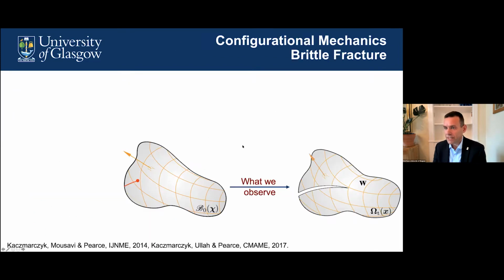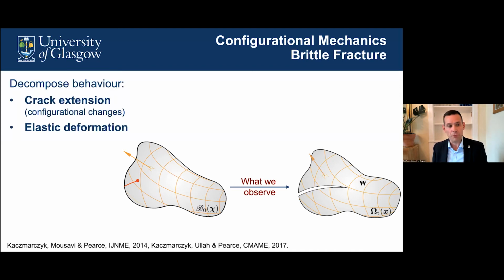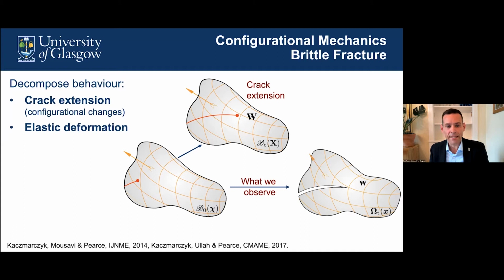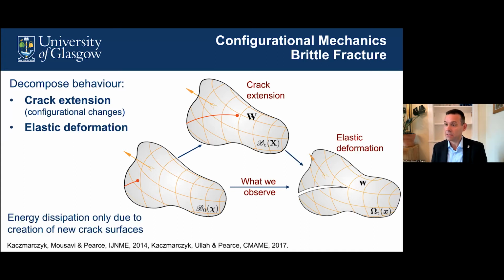Configurational mechanics in a nutshell: if we take a body subjected to load, what we observe is elastic deformation and crack propagation. What configurational mechanics allows us to do is to decompose the problem into a crack extension and the elastic deformation. We decompose the problem into these two cases, whereby all the energy dissipation is only due to the creation of new crack surfaces. So we're dealing purely with linear elastic brittle fracture.